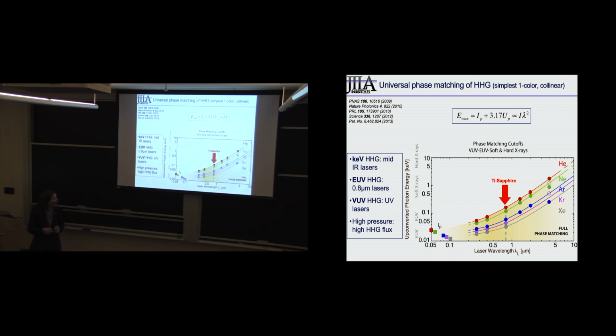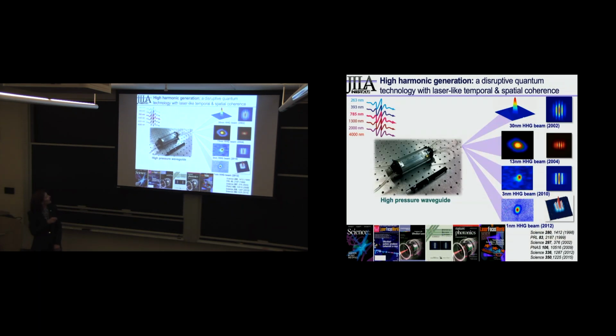And so practically what we do is we use different color lasers from the ultraviolet through the mid-infrared and near-infrared. We focus into a gas-filled waveguide, and then we get short wavelength beams that go from the vacuum ultraviolet to a nanometer now. And with reasonable conversion efficiency of about 10 to the minus 5, 10 to the minus 6. So if we use a 10 watt laser, we get microwatts of power in the EUV, and that's fine for spectroscopy and for imaging.